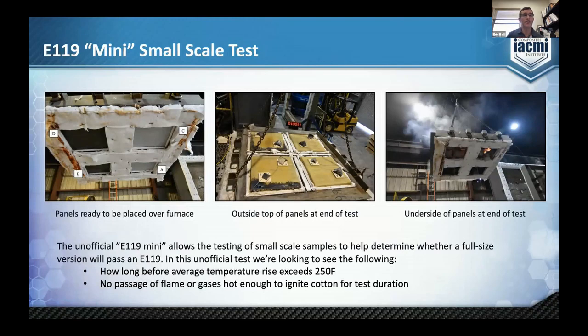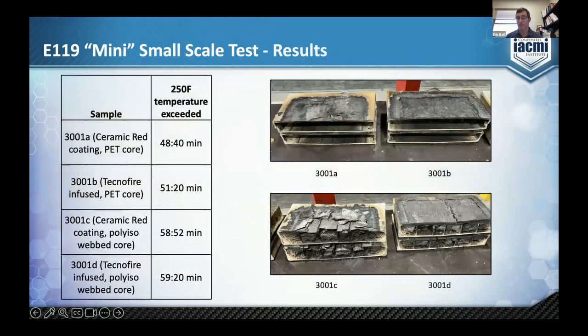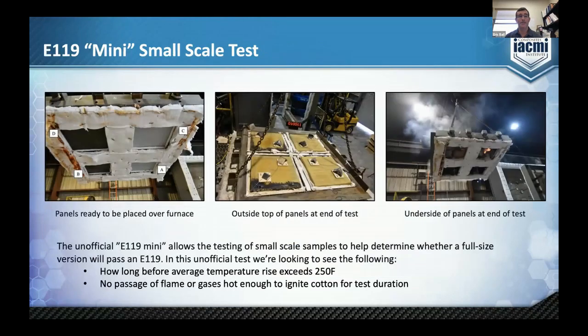On the left, you can see before the test is started, that middle one is in the middle of the test, and then at the end of the test, you can see the panels being pulled up, and you can see some of it still on fire there. So to pass this test, the temperature on the back side, on the non-exposed side, can't exceed a temperature rise of 250, and you can't have any passage of any flames.